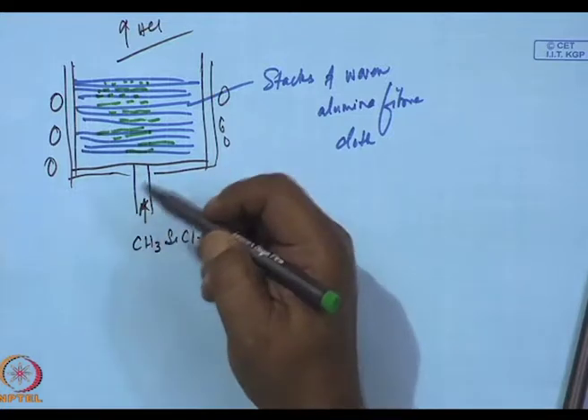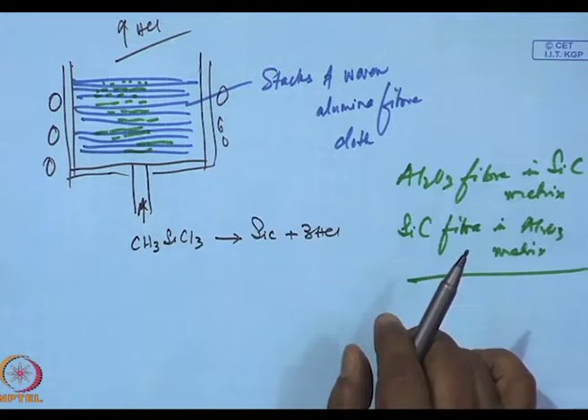So, of course, this is still not impervious. It has to be taken out, machined to clean the pores, and again infiltrated to get a very dense matrix. So by changing, I can get Al2O3 fiber in SiC matrix. I can get SiC fiber in Al2O3 matrix. I can get any one of them. I can switch depending on what I use, both of them.